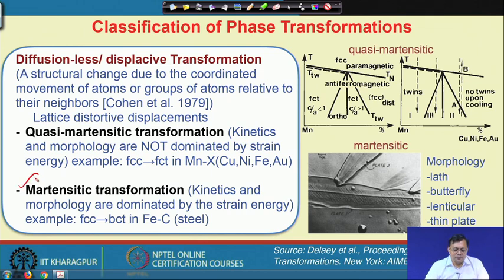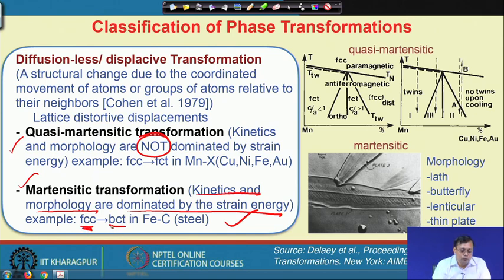In case of martensitic transformation, be very specific that kinetics and morphology of the product phase are dominated by the strain energy, which is not the case in quasi-martensitic. So, it means that strain energy must be higher in case of martensitic transformation. We will slowly discuss what they are. An example is an FCC phase that transforms into body centered tetragonal in case of a steel. It is an iron carbon system, a very common example that you all know.